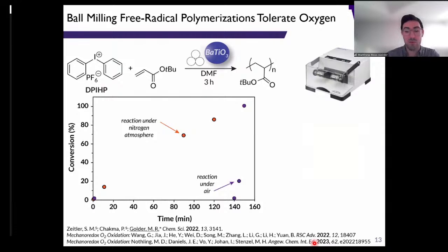We can set these free radical polymerizations up either under a nitrogen atmosphere in the glove box or under air on the benchtop. But what we noticed is that the kinetic profiles for monomer consumption, so monomer consumption is on the y-axis here and reaction time is on the x-axis.